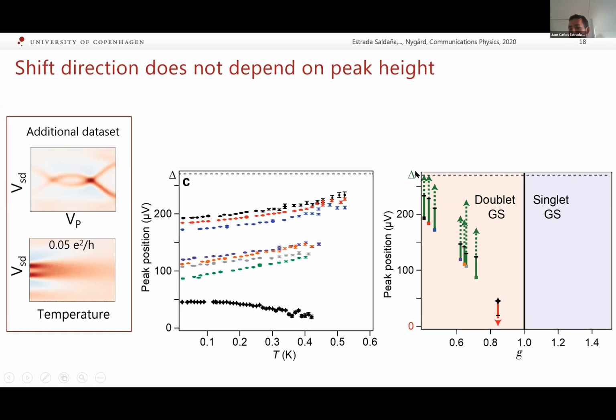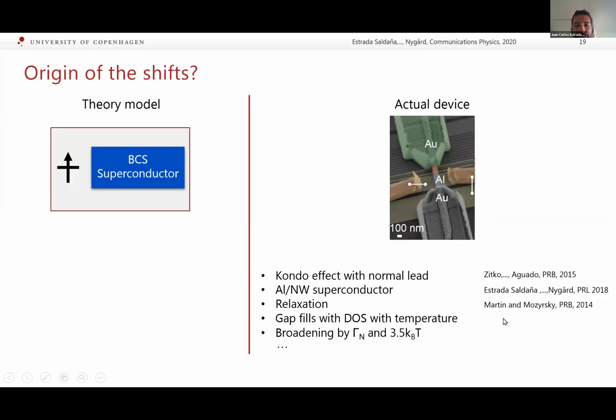And again, the same parameterization gives us the same result. We have a change of the direction of the shift with temperature on the doublet side. So just before the doublet to singlet ground state transition, there is a red arrow going downwards. So this is the last slide before the conclusions. And if we want to think about what is the origin of these shifts, I suggest that we should compare the theory model to the actual device.